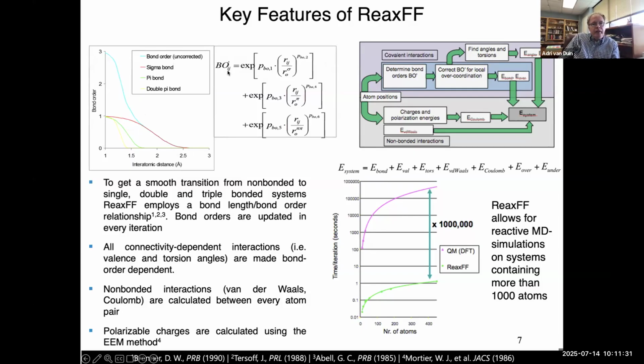And with that concept, we can essentially plug in the interatomic distances into this equation. A bond order comes out, we can calculate associated forces, and we can do molecular dynamics where we break and make bonds during the simulation. Now we know clearly from non-reactive organic force fields that angle and dihedral interactions are very important to consider. So we include those in ReaxFF as well, but we make them bond order dependent. So we multiply an angle term by a bond order term. So if the bond order goes to 0, the angle term automatically goes to 0 as well.